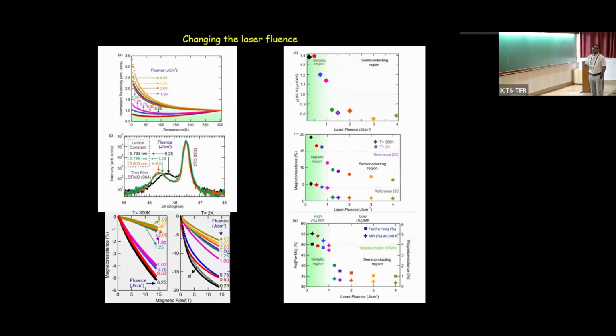So we changed the laser fluence, used different laser fluences, and this is the resistivity as a function of temperature. And we have seen that if you change the laser fluence, there is an insulator to metal transition in the system. And this is the magnetoresistance. I'm not going into the XRD data. There is a crystallographic change in this. That will be evident from this next graph.